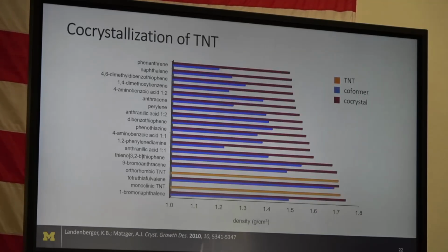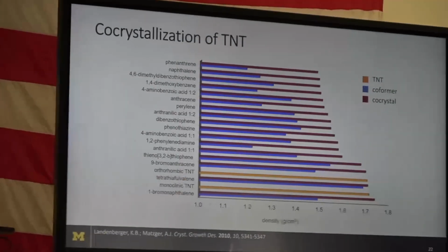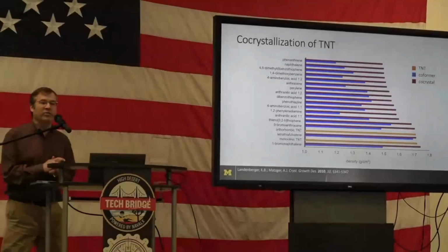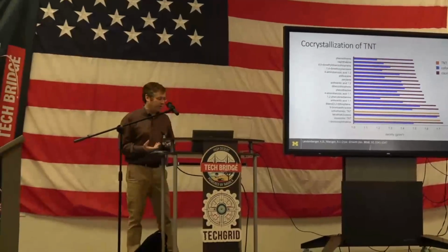So now with this basis we could start looking at properties and see what kinds of properties we were getting. I've shown here the co-crystal density and then the co-former density. You can see TNT already, orthorhombic and monoclinic TNT, they're way up here, reasonably dense. But we did find a few cases here at the edge, like with bromonaphthalene and with tetrathiafulvalene, which is a very electron-rich molecule, where we were able to make something more dense than either of the two things that went into that co-crystal. And we thought, well, now that's pretty interesting. We're not always getting an averaging of properties. We might get new properties emerging.